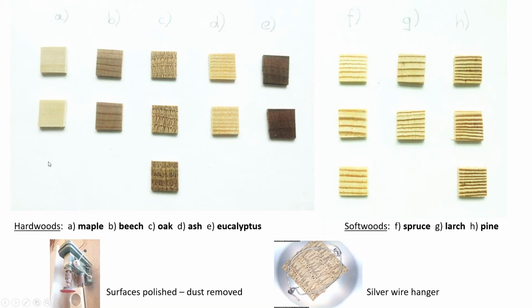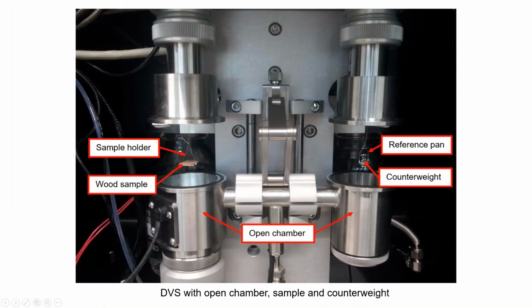She prepared this type of samples. She polished the surface and removed the dust with this grinding machine, polishing with high grit paper, and we didn't use the quartz hanger that we had purchased from SMS. By recommendation of the experts of SMS, we produced a self-made hanger using a silver wire, because we are looking from beneath with the video camera onto it, which we see in the next picture of our setup.